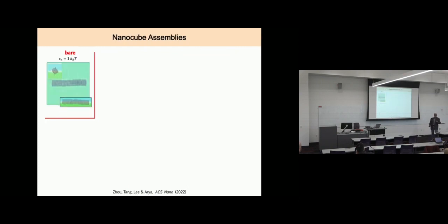It does give rise to some interesting structures that you wouldn't see with spherical particles. The bare particles themselves are very interesting. It wants to be formed edge up, but if it's edge up, you have only vertices in contact, which is very bad. It's not going to form because vertex-vertex interactions are very weak. So what is this guy going to do? It's going to turn itself to face up, which is not as favorable, but at least in the face up configuration, it has these faces through which it can interact. So it's going to form these linear chains. In fact, this is a fantastic way to create linear chains of metallic nanoparticles, which could actually be a real synthesis protocol.